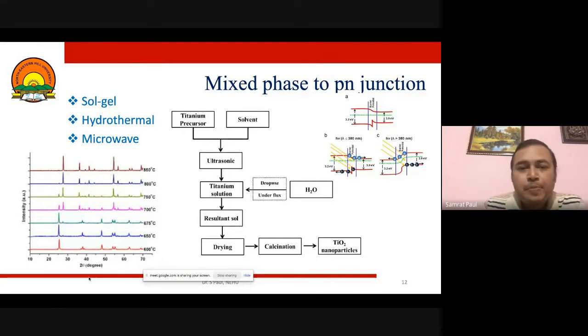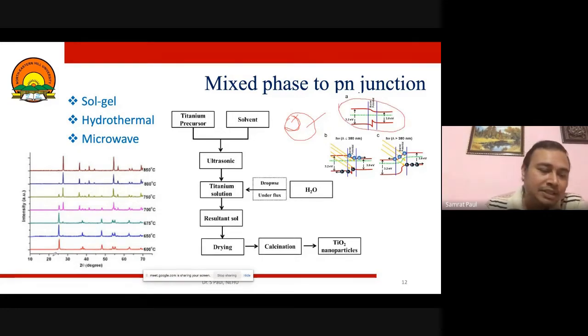So we can see in the same material, if we can have both the phases, means if there is a titanium oxide particle, and there is some anatase phase, and there is some rutile phase, so we'll have what in the junction? We'll have a PN junction, as I have shown here. So how we can make them? While synthesizing, we found that, so this is the anatase phase. This is the XRD data, anatase phase, and this is the rutile phase.